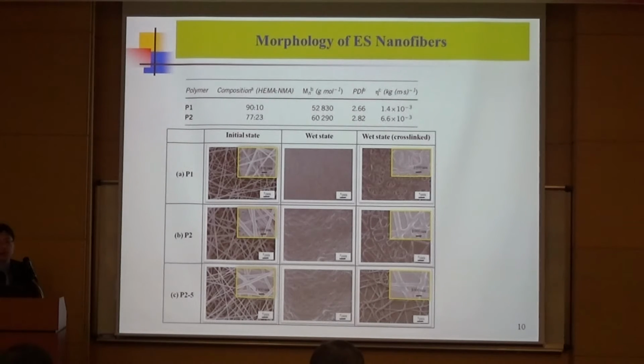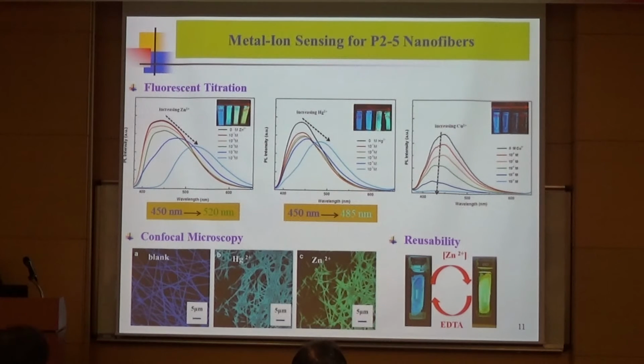Without thermal cross-linking treatment, these nanofibers cannot maintain their fibrous morphology after immersion in aqueous solution. However, after the thermal cross-linking treatment, these nanofibers, only those with the higher NMA content, can remain in their fibrous conformation in aqueous solution, with good swelling of water to a much larger diameter, around 1 micron. So then we study the fluorescence titration behavior of these P2-5 blending nanofibers against three different types of metal ions.